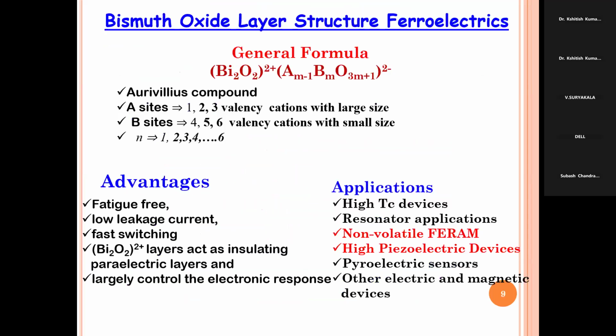So the bismuth layer structure, the general formula we have written is the bismuth oxide layer, and A(m-1)B(m)O(3m+1). A is the A-site cation, B is the B-site cation, and O is oxygen. And this material is also called Aurivillius compounds. The A site has 1, 2, 3 valency cations on the larger side, that means strontium, calcium, then barium in the periodic table, these are present at the A site. And the B site has 4, 5, 6 valency cations, that means titanium, then tantalum, niobium.